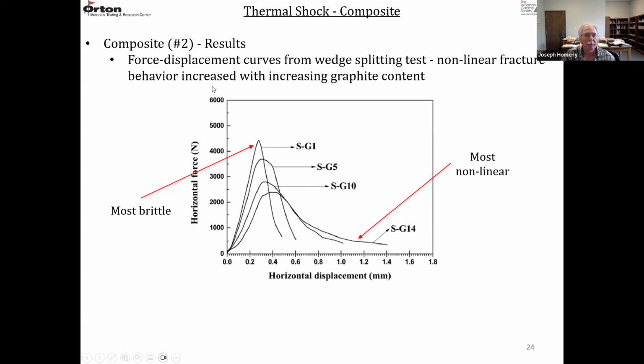And when they run the wedge splitting test, this is the horizontal force versus the horizontal displacement. You have this nonlinear fracture behavior that becomes more nonlinear as the graphite content goes up. So this is SG1, SG5, SG10, and SG14. So the higher the carbon or graphite content, the lower the strength, but the bigger the area under these low displacement curves, and the more nonlinear the behavior becomes with higher graphite content. So SG1 is pretty linear. It's the most brittle. And then SG14 is the most ductile or the most nonlinear.